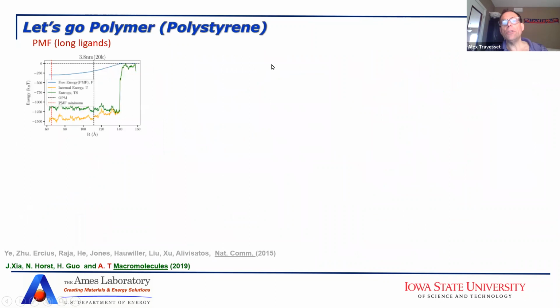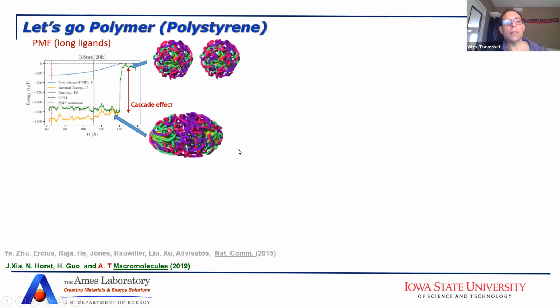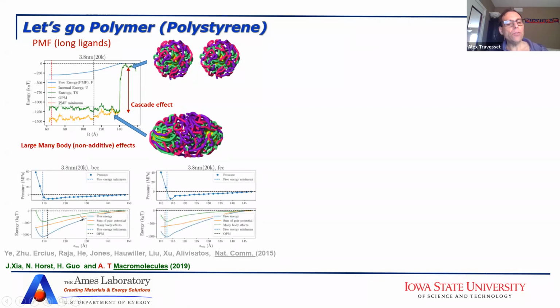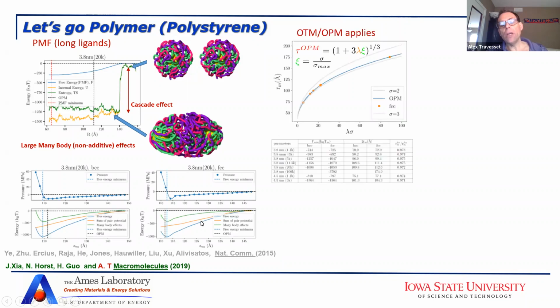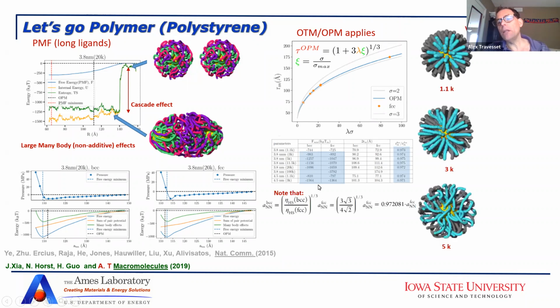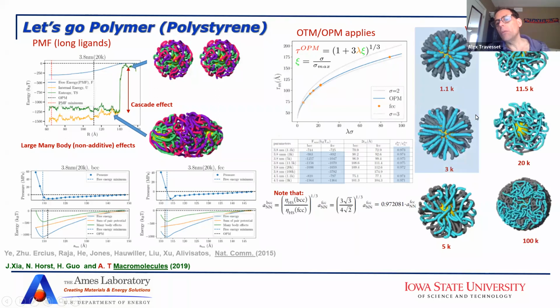When you go to polymers, there is a situation where many things happen. For example, when you have long polymers, the nanoparticles are able to form the many-body interaction. The mean field is actually quite complex, because when the polymers are sufficiently long, they can form this type of structure that we call the cascade effect. The free energies follow more complicated formulas, but at the end, those can also be successfully described by the OTM, even for very long polymers, which corresponds to nanoparticles that are functionalized with polystyrene. The free energies follow the same aspect, and we can even identify vortices. When the chains are short, we get the usual vortices, but then as you start going larger, they become a little more complicated, but at the end, they follow the same procedure. So even if you go to the polymer limit, they are also well described this way.